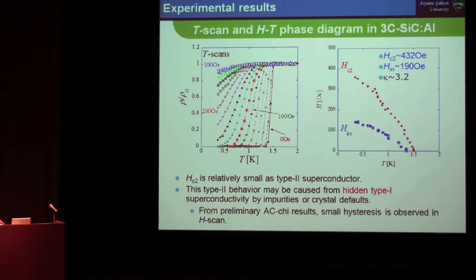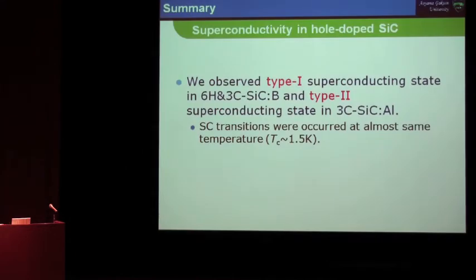This is a T-scan and phase diagram in 3C aluminum-doped silicon carbide. We observed the type 1 superconducting state in 6H and 3C boron-doped silicon carbide, and type 2 superconducting state in the 3C aluminum-doped silicon carbide. Surprisingly, or unfortunately, the transition temperature is almost the same.